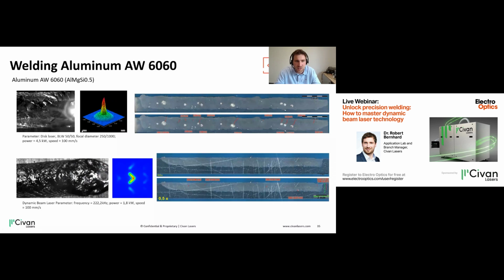With our dynamic beam laser, we're actually able to do the welding and make sure, by a specific beam shape, here it looks like a boomerang kind of, that keeps the keyhole open and distributes the energy just right in order to get the melt pool and the material to flow beneficially for our process. So despite the scratches on the part, it's a very nice weld in terms of the penetration uniformity as well as porosity.